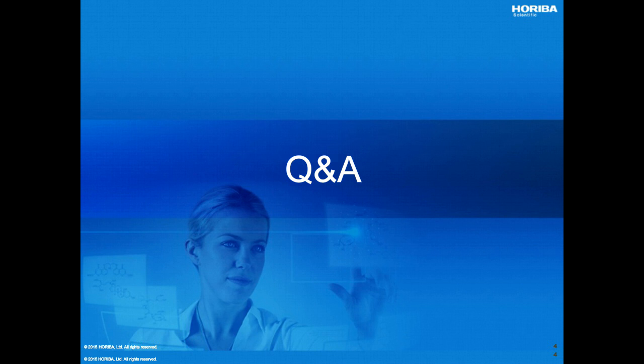What is the chi-square value of your fitting for P3HT and PCBM? To give a more general answer for chi-squared values, we want chi-squared to be around 1. Some materials will be a little more complex and we'll get a slightly higher chi-squared, but we generally want to make modifications to the model to get a good chi-squared around 1. I don't have the specific values for P3HT and PCBM, but I'm sure they were pretty close, below about 5.